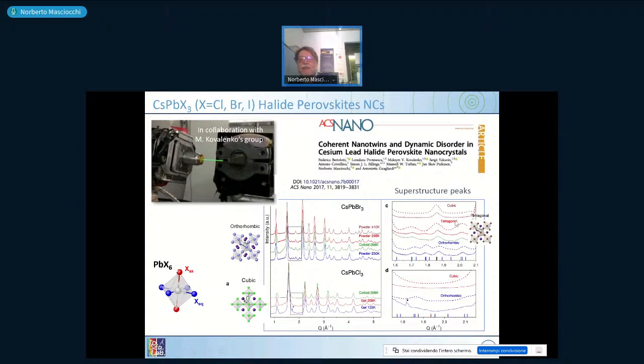In the plot to the right, you have the observed data, which are the solid lines, and the computed data for the different structures which were observed in a perovskite single crystal. As you can see, when you have a cubic system, you have only one peak here. When you have a tetragonal system, then you clearly have three peaks here, four measured in our system. When you have an orthorhombic one, the number of peaks increases and falls exactly where the peaks are observed.